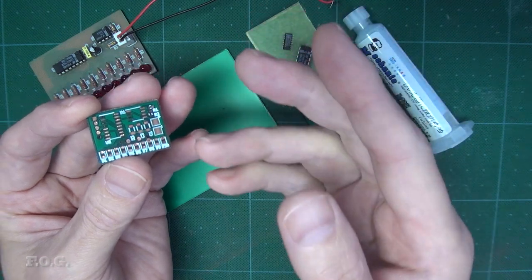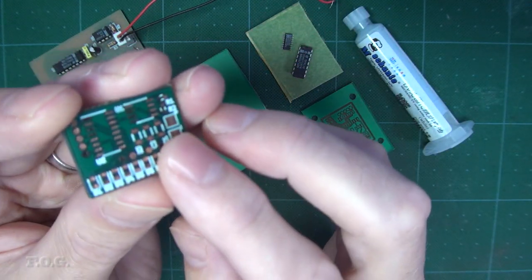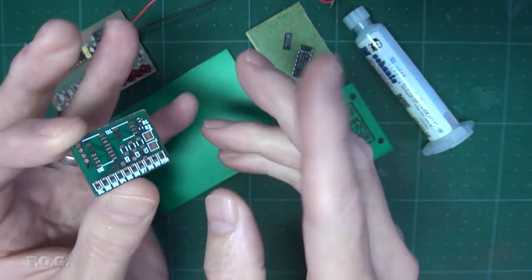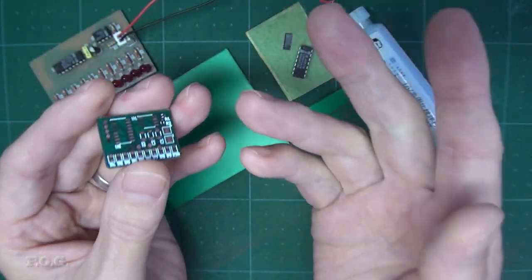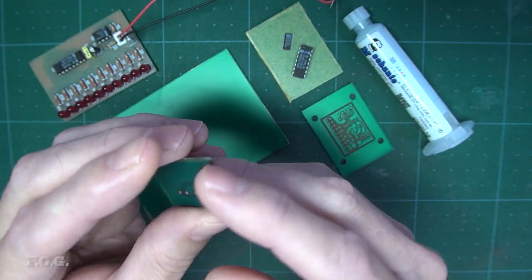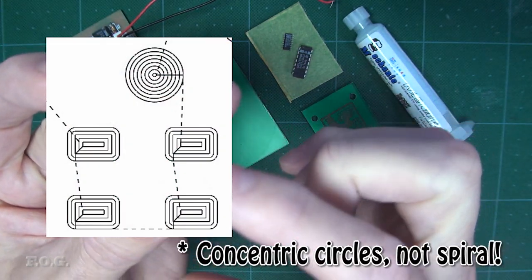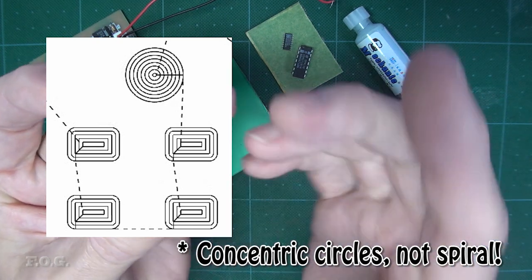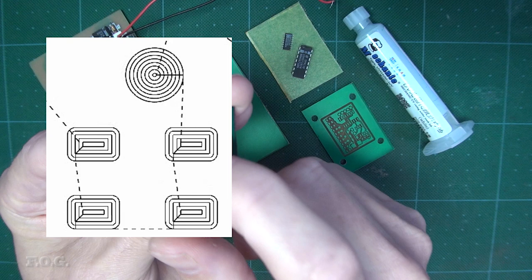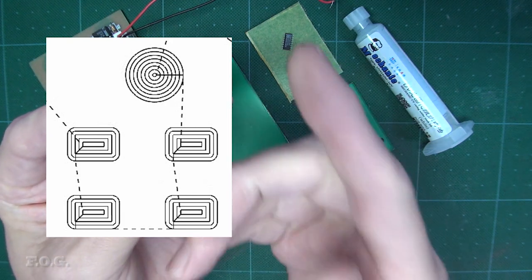Anyway to clear the pads in the next try I will reduce the power from 40% down to 25% and see how that goes. I'm really just guessing here but hopefully it will be in the ballpark. I'm also going to try a different pattern to clear the pads. Up until now I've been using a spiral method that clears from the center to the outside or vice versa, but I'm starting to think that this method actually causes a concentrated heat buildup at the center of the pad. Naturally that's bad.